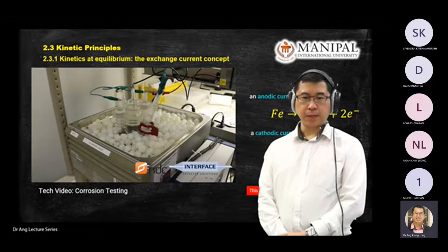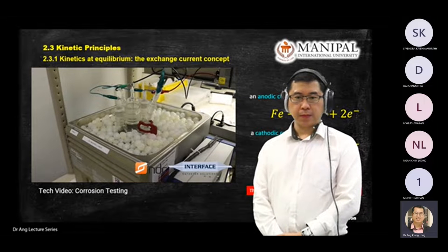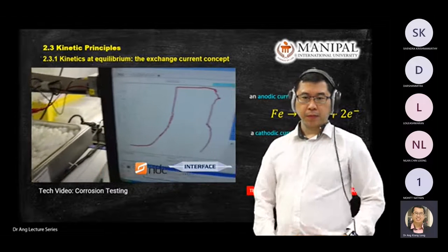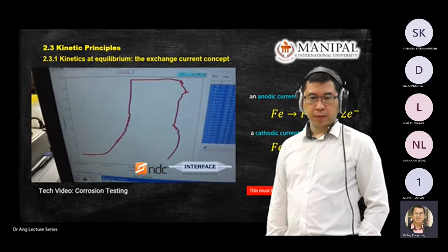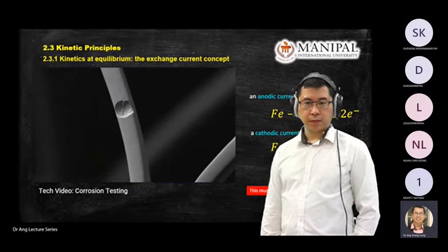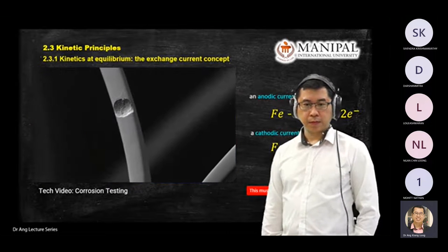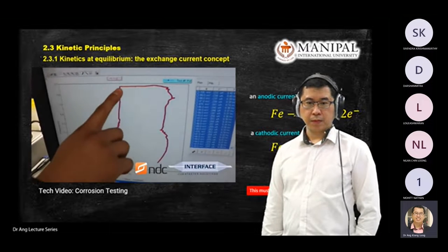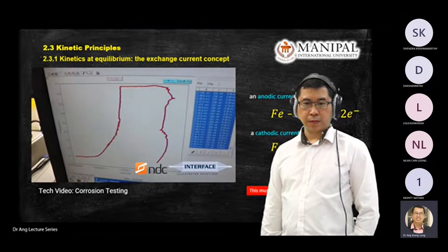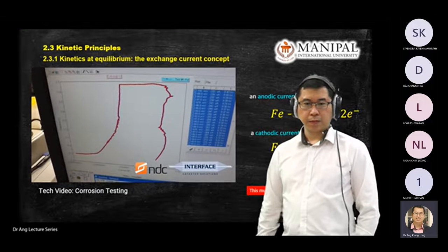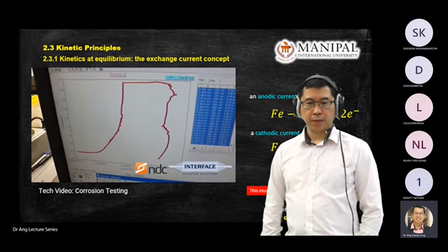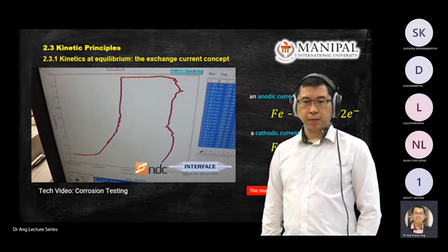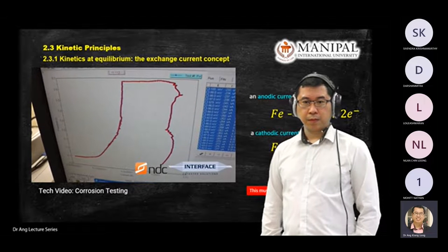And the potentiostat will then increase the voltage gradually over time. And then one of two things will occur as a result of the increase in voltage. The first thing that can happen is a pit can form on the part. And we know that a pit forms because you see this current spike here at the top. And that potential is what's known as the breakdown potential. So the higher the breakdown potential, the better your implant is at resisting corrosion.